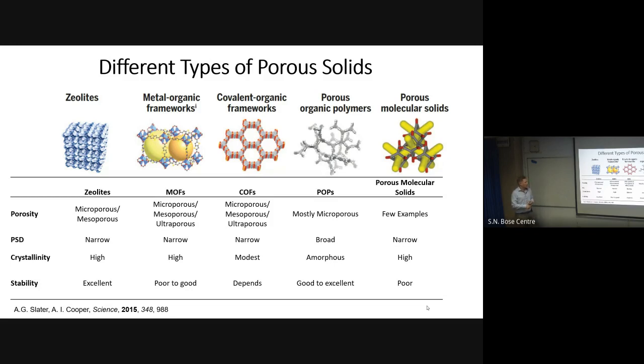Metal organic frameworks, a topic that Cardiff is also very familiar with, have some advantages over the zeolites. They can have ultra high porosity because you put in these linker molecules, these spacers, between the metal sites, and you still have very crystalline materials. But their stability is lacking because you only have coordination bonds to keep these porous crystalline frameworks together.